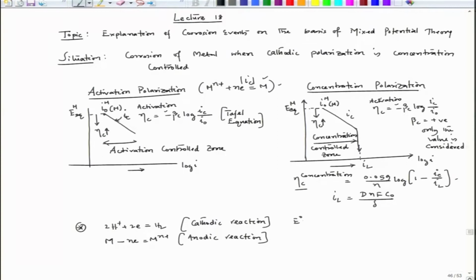And here E0 of H2 equal to 0. So, E0 of M n+/M is less than 0, and of course, in the electrolyte, depending on the pH value of that solution, I can have a situation where E equilibrium of hydrogen evolution can be greater than E equilibrium of the metal. In that situation, of course, hydrogen evolution will be the cathodic reaction and metal dissolution will be the anodic reaction. So, let us see what would happen there.